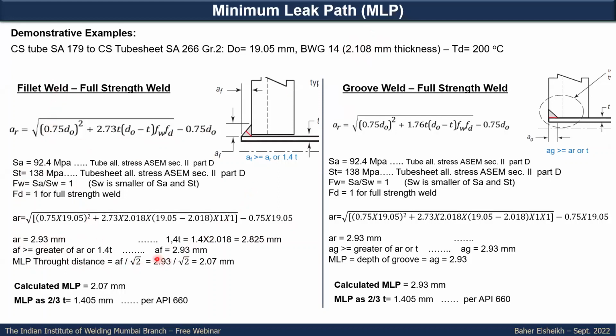And as per the recommendation for the fillet, a_f, this one, should be the greater of 1.4t or the a_r. So 1.4t here is 2.825. So a_r is higher than 1.4t. So a_f will be 2.93 like the a_r. The minimum leak path here from the design perspective will be this, the throat. So we calculate the throat as a_f over square root of 2. So it will be 2.07. So from this calculation, if we respect to meet the design code, this is the minimum leak path for the design configuration. So in this case, the minimum leak path is 2.07 mm. If we check as per API 660, the 2/3 of the thickness is 1.405. So the method we are following in this calculation is much more stringent and conservative compared to the 2/3 of API 660.